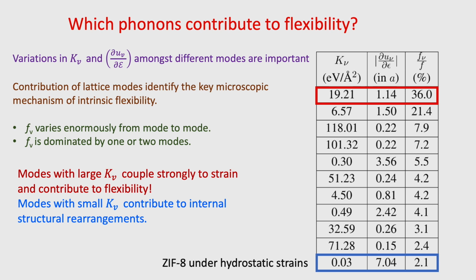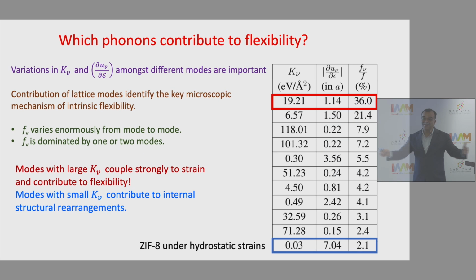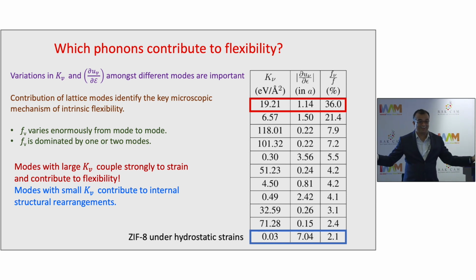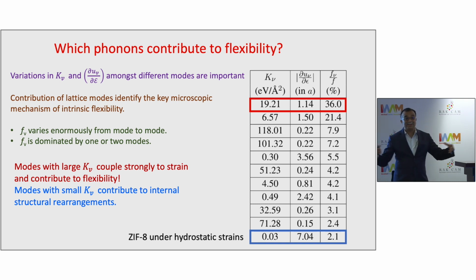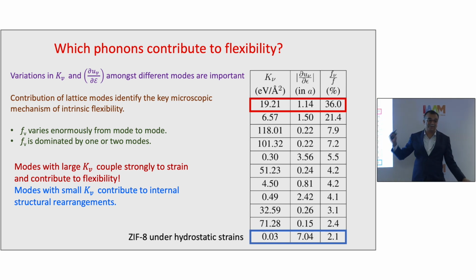36% of the flexibility comes from the intermediate frequency. This is the spring constant of a phonon, and low frequency modes typically contribute less, but they give much larger internal structural displacement. See, this is the key point I want to highlight here. Soft phonons help in large internal structural relaxation, giving you large deformation in length scale. But they cost very little energy. When you apply stress, that energy has to be absorbed by someone. And that role is played by the high frequency phonons.